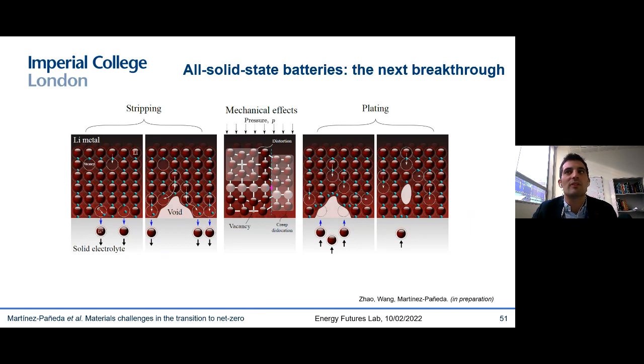And without getting too deep into the details, I would say that the model has three main ingredients. The first one is vacancy diffusion, so we can capture surface and bulk substitutional lithium diffusion within the lithium metal anode. The second one is the mechanical behavior of anode and electrolyte, and this includes the viscoplastic nature of lithium metal, so that allows us to capture creep effects. And third, we can capture the annihilation and nucleation of vacancies, which is basically what governs the void evolution. And for this last ingredient, we make use of that phase field paradigm that I was presenting before, and that constitutes basically the backbone of all these models, as it allows us to track interface evolution.